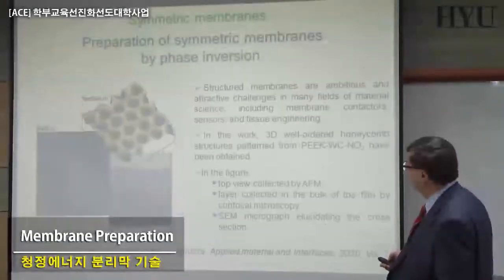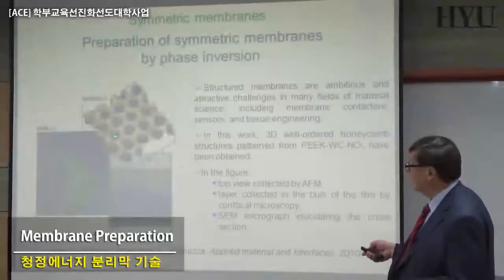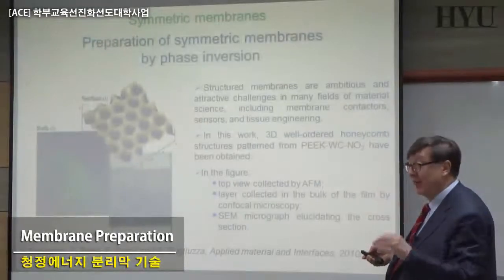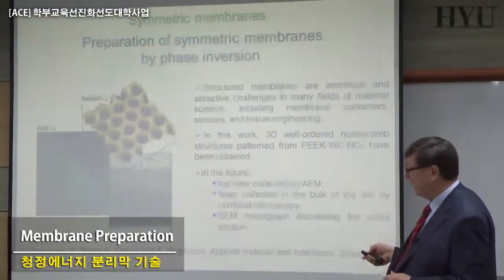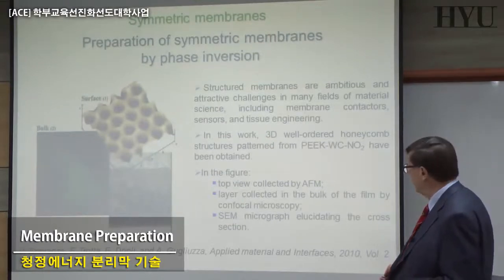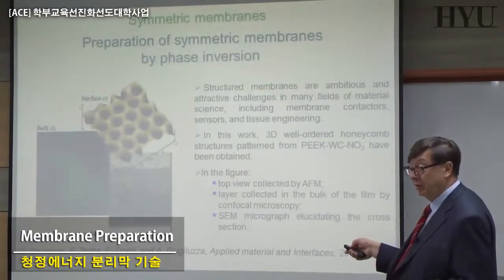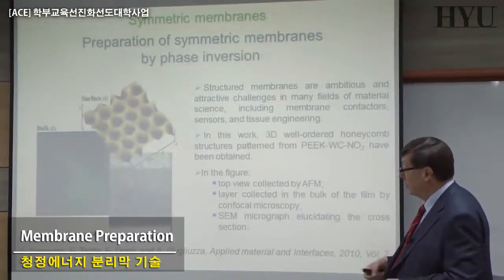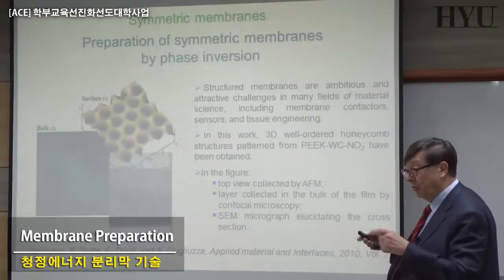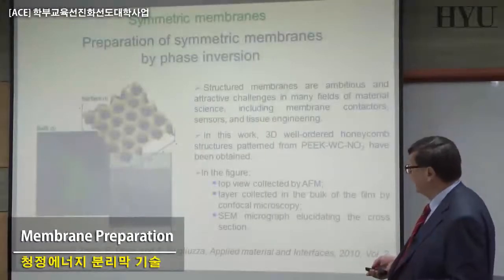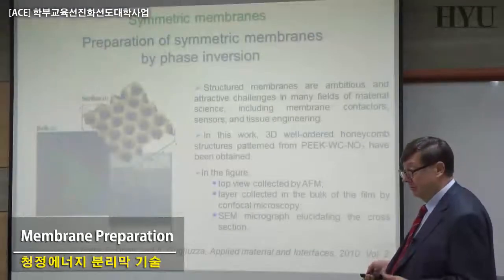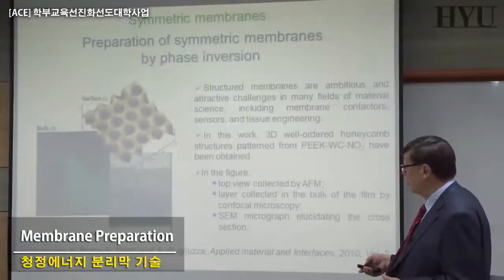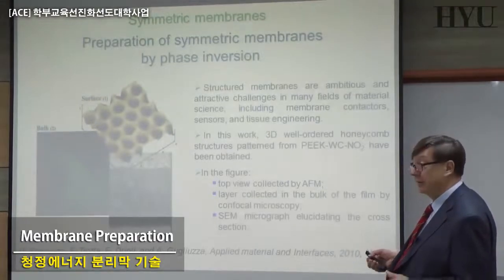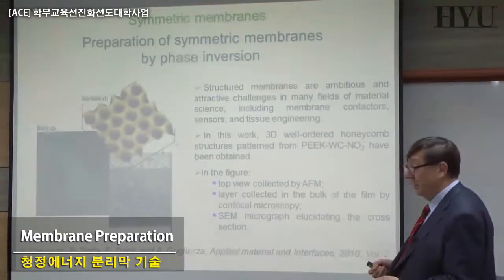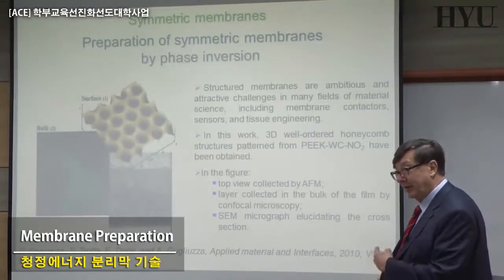And we can also change the size of the pore, or have dense membranes, and that is a typical case you can see here. And this is another case in which, using a modified phase inversion, a lot is still to be done in this line, but that's something we already published a few years ago, you can have a very nice homogeneous pore size distribution. If you're able to produce on large scale a roll-to-roll film of this kind, a lot of problems in principle can be solved. However, that is just typical of a paper, there are no membranes of this kind available. There's a lot of work to be done because mechanical properties are still low, they will break easily. So in the paper, nothing happened, but in real life a lot of trouble exists.